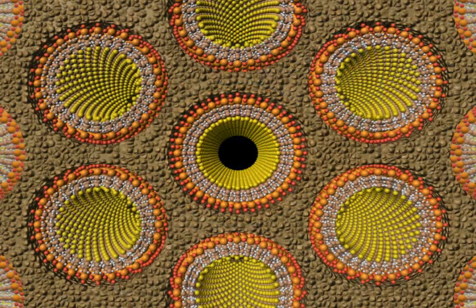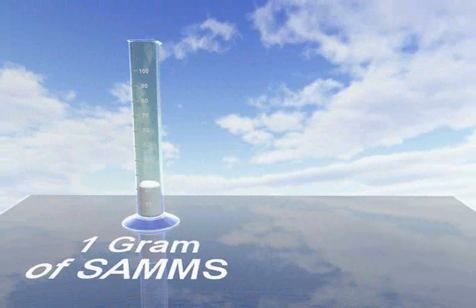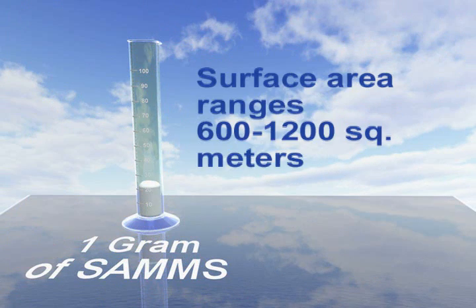The family of SAMMS sorbents developed by Battelle consists of mesoporous substrates with surface area ranging from 600 to 1200 square meters for every gram of material.